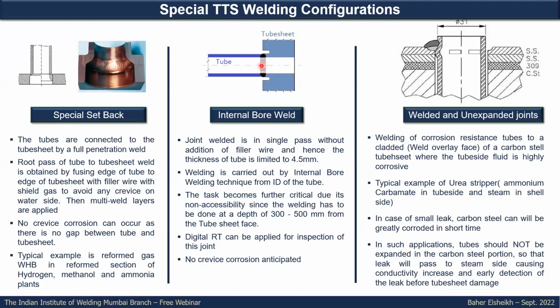This butt weld has many advantages. You will not have the crevice here between the tube and tube sheet, and you can also apply the proper inspection using digital RT or UT for the weld joints. So you will have very good confidence in the quality of the applied weld as well. And this welding joint is one of the special recommendations where there is some cladding material of special alloy here, and the tube also with the same material, while the tube sheet is carbon steel.